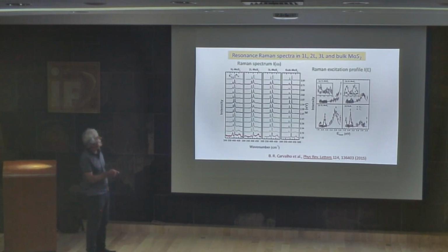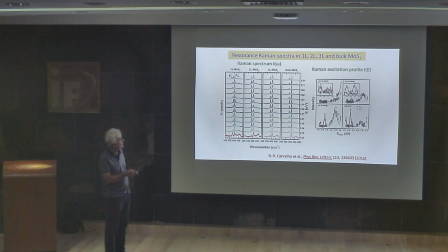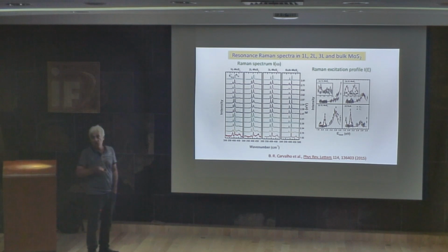Okay, now this is the resonant Raman spectra of MoS2. We did that; this was the paper of Bruno Carvalho. Then we have 1 layer, 2 layers, 3 layers, and bulk. As I showed you, using many different laser lines, the colors of the spectra follow the color of the laser. And here is what I call the resonant Raman excitation profile. For example, here I have this A mode, the so-called out-of-plane mode, and the E mode is the in-plane mode.